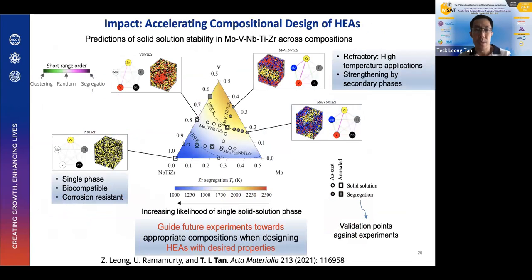And we can use this for design. Suppose we want to study different compositions of high entropy alloys. Do we know which composition will lead to phase separation? Which compositions will have a higher chance of having a single phase? For example, niobium, titanium, zirconium is a ternary, and there's some interest in using this for biocompatible applications. Here it is important that this material is a single phase, because for alloys, if you have 2 phases, it might not be corrosion resistant. If we are going to use this for, say, bioimplants, then this material needs to be fairly corrosion resistant.